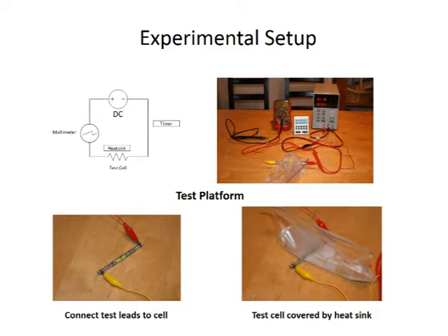The early results were disappointing. It takes quite some time to fully cycle a cell through the range of voltages, and none of the cells showed memristive effects on their first cycle. It was only after some time I came back and retried some early cells that they showed memristance. This was confusing, but on further investigation, I found research stating that some memristors require a forming step before they will exhibit memristive behavior.